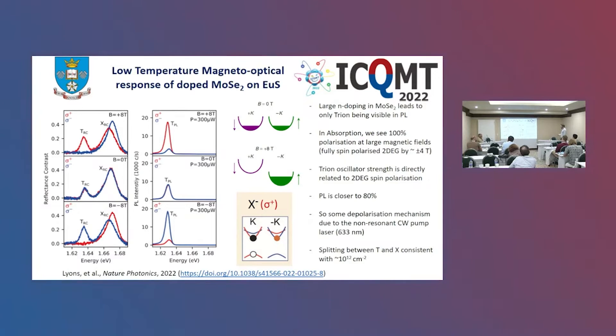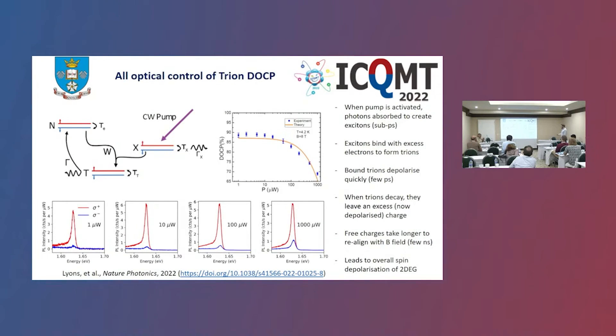We see the PL is closer to 80% degree of circular polarization compared to 100% in the reflectance contrast, indicating some depolarization due to the non-resonant circularly polarized pump laser. This is captured in our rate equation: when the pump is activated, excitons form on a sub-picosecond timescale, then bind with excess electrons to form trions. These intervalley trions depolarize quickly over a few picoseconds. When they decay, they leave a depolarized excess electron, and free charges take a much longer time — on the order of nanoseconds — to realign with the magnetic field. The ratio between depolarization and repolarization is about a factor of one thousand.